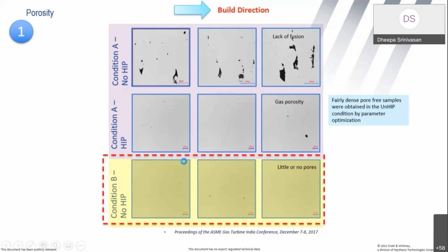So we tried both with HIP and without hot isostatic pressing, and based on this DOE, between a month and a half we were able to go from this particular top row to the bottom row without HIP. So this material here at the bottom most became our new norm in order to test other factors towards qualification of this particular idea of having an additively manufactured near net shape part and an investment cast dissimilar material, because remember, this is cobalt chromoly, that is cobalt tungsten alloy, both of these joined together. So that is what we proceeded.